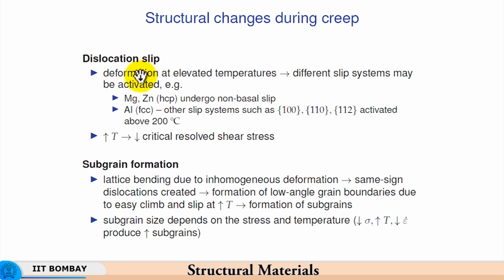When you have dislocation slip taking place, Mg and Zn undergo non-basal slip. Normally, basal planes of the hexagonal close pack structure are one of the most favored planes for slip, particularly when the temperatures are relatively low. The slip systems involving the basal planes of the HCP crystal are very active, but as the temperature increases, different slip systems like non-basal, that is prismatic slip systems, get activated and can take over. So the resistance to creep deformation will change depending upon the plane on which slipping is going to take place.